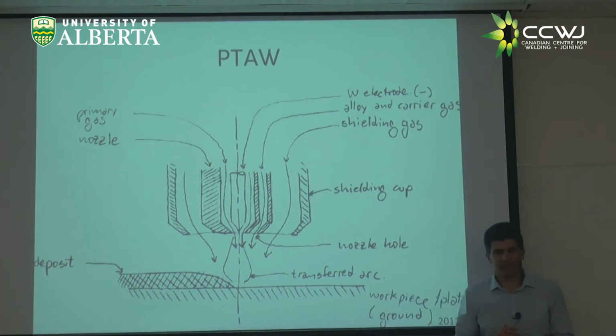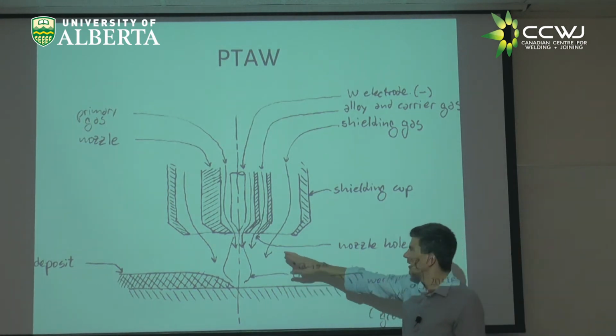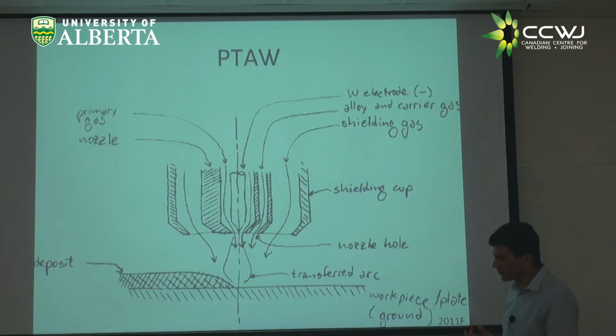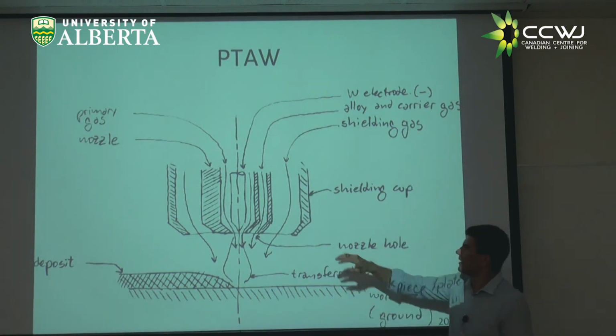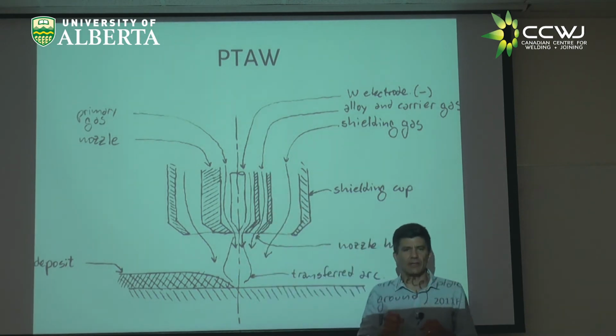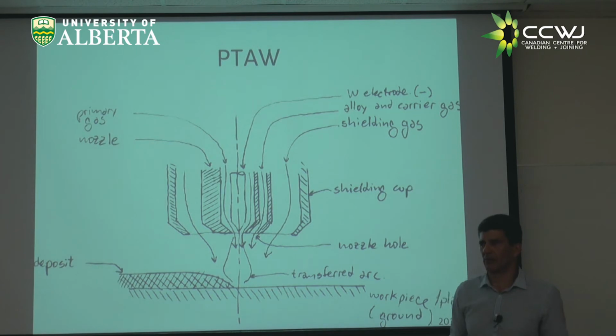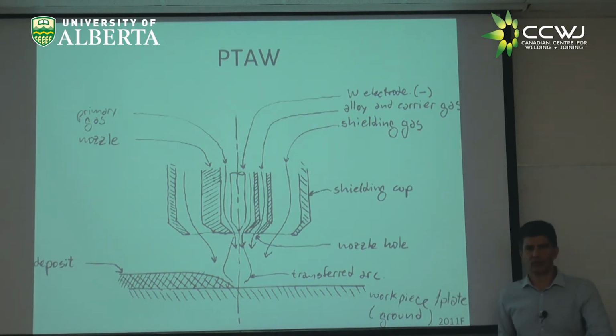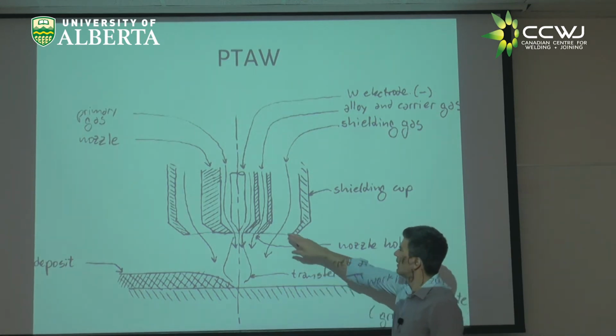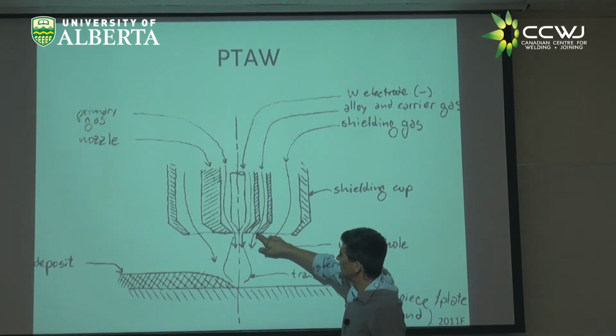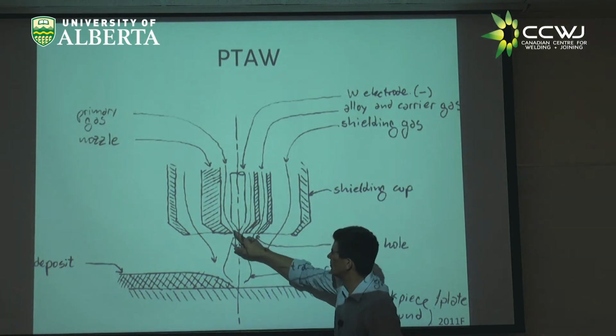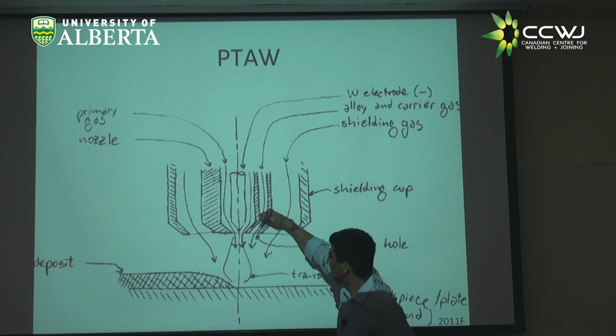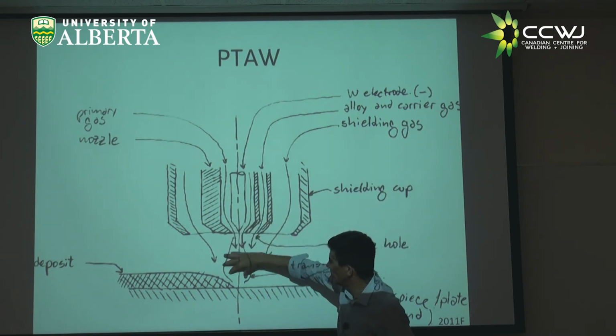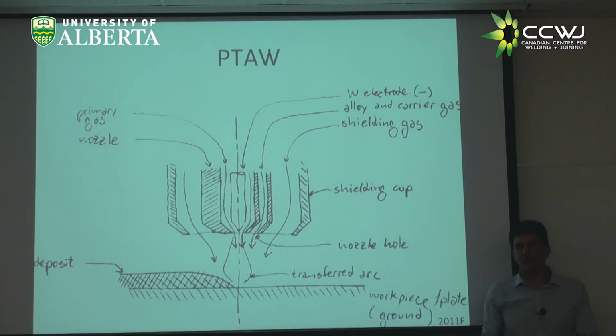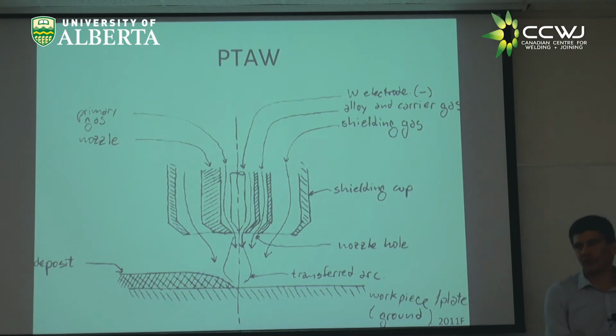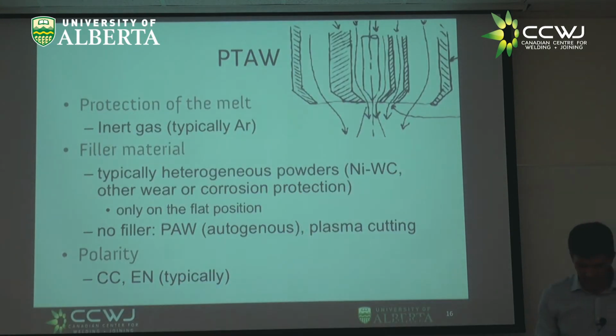Now, what we do in this process, in addition to this plasma process, is we have a third flow of gas that is called the carrier gas. And this carrier gas can bring powders, and we can then deposit powders and do additive manufacturing, or put corrosion protection coatings, or wear protection coatings, right? So you have a third flow of gas. And here, in the nozzle, you would have either 2, 4, or very many holes, and the powder comes out of here, gets molten in the arc, falls here, and you have a process in which you have a filler metal, right? But you have no wires or anything like that. You're going to see this in action.